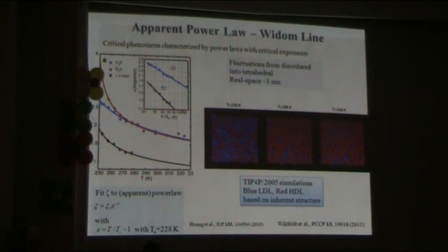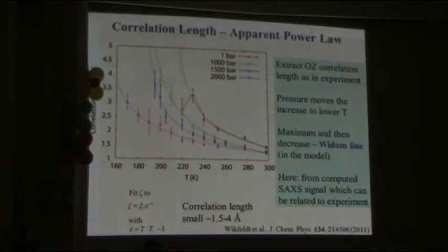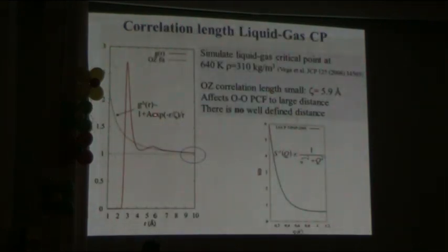Now, the other aspect here is that the correlation lengths are very small. They're of the order 2 to 3 angstrom, so how can that be important at all? Well, one has to remember that in Ornstein-Zernike theory, what one looks at is the first term in the asymptotic expansion going to small q. So the correlation length in real space corresponds to the asymptotic behavior at large R. And that corresponds to this exponential decay.